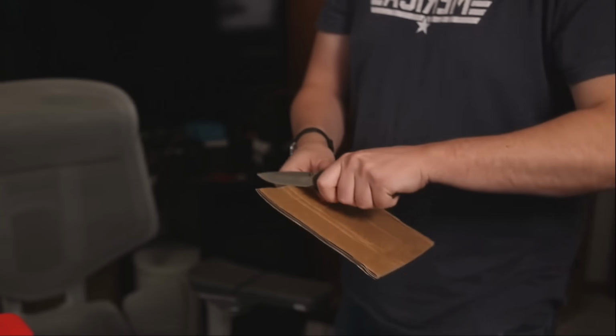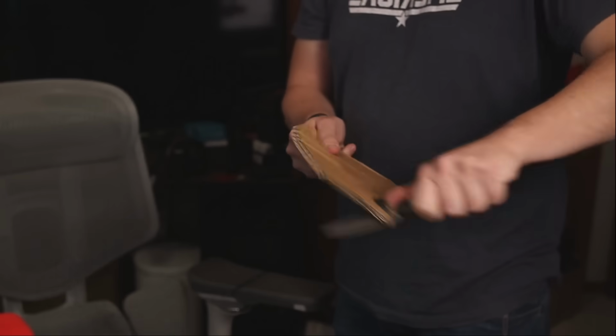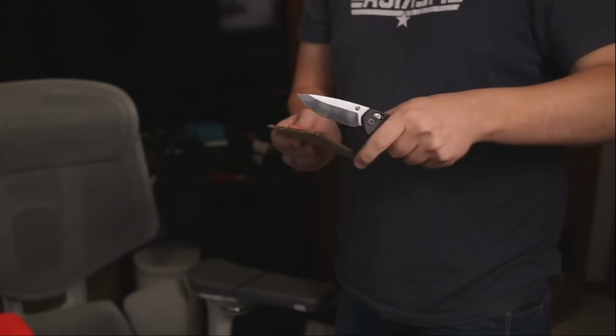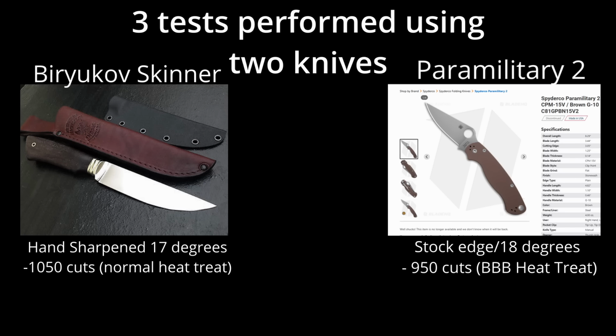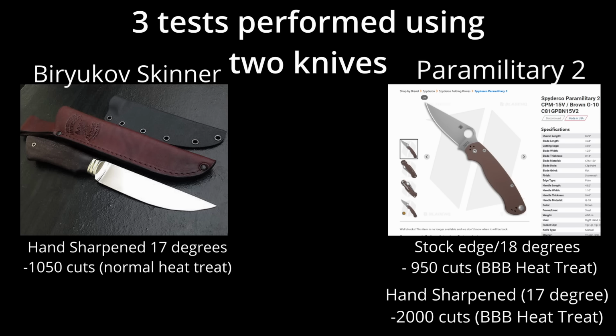Belt ground edges almost never outperform a hand-sharpened edge with the same edge geometry, let alone one that is 1 degree less per side. The next cut test proves this because Pete put a hand-sharpened and polished 17-degree edge on that very same Paramilitary 2 that just prior had only attained 950 cuts. After dropping the geometry and sharpening by hand, the 15V Paramilitary 2 absolutely blew every other knife on the datasheet out of the water with a whopping 2,000 cuts.